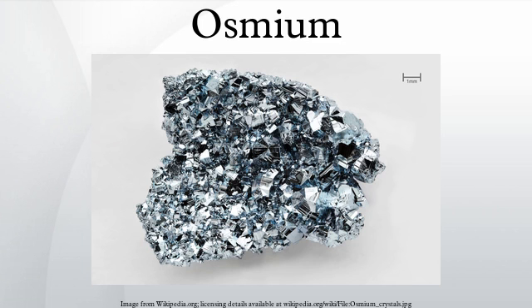Osmium is a hard but brittle metal that remains lustrous even at high temperatures. It has a very low compressibility. Correspondingly, its bulk modulus is extremely high, reported between 395 and 462 GPa, which rivals that of diamond. The hardness of osmium is moderately high at 4 GPa. Because of its hardness, brittleness, low vapor pressure, and very high melting point, solid osmium is difficult to machine, form, or work.